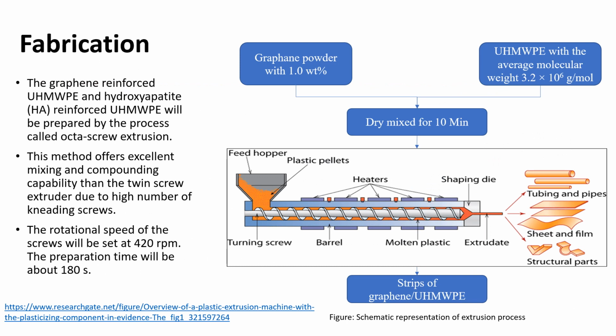So now we'll look at how graphene and hydroxyapatite reinforced ultra-high molecular weight polyethylene will be fabricated. This composite will be prepared by a process called octa screw extrusion. This method offers excellent mixing compared to single or twin screw extruders due to the high number of kneading screws. So the 1.0 weight percent powder of graphene and ultra-high molecular weight polyethylene with an average molecular weight of 3.2 x 10^6 g/mol will be dry mixed for 10 minutes to improve the dispersion. After that, the mixed powder will be placed in the octa screw extruder to produce strips of the graphene and ultra-high molecular weight polyethylene composite.